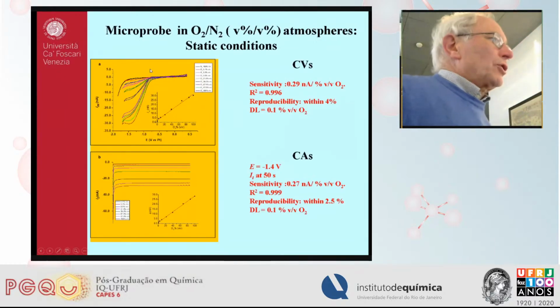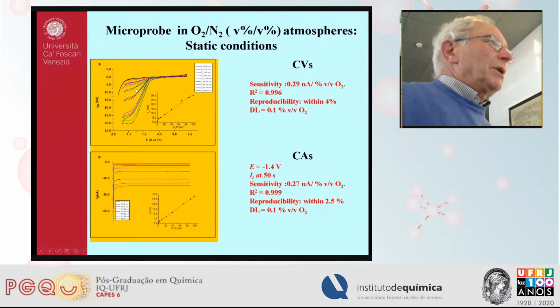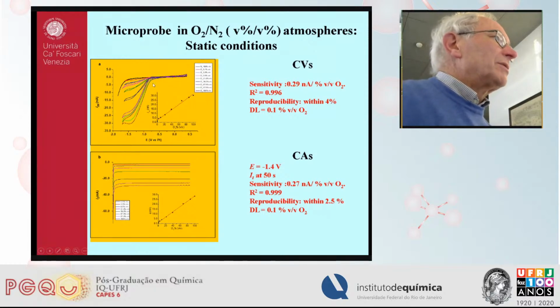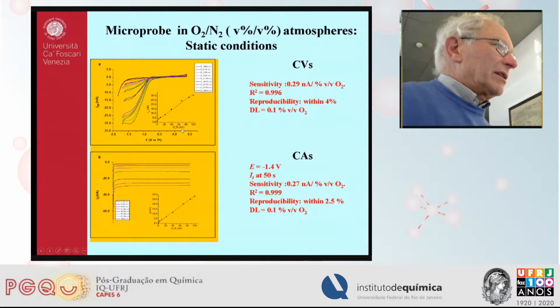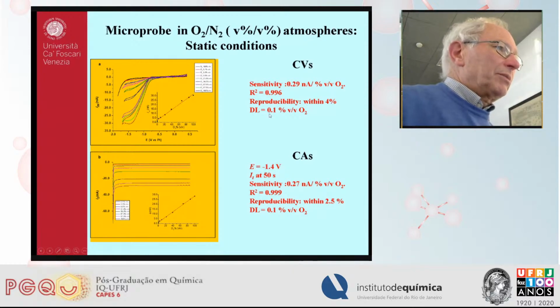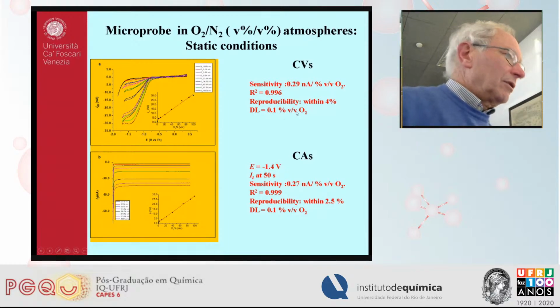This is a sort of calibration plot we obtained by doing measurements with the probe using cyclic voltammetry in different mixtures of oxygen and nitrogen. So by plotting the peak current of this CV against the percentage of oxygen in the mixture, we obtain a very nice linear calibration plot. The reproducibility was within 4%, very good. Detection limit down to 0.1% v/v oxygen.